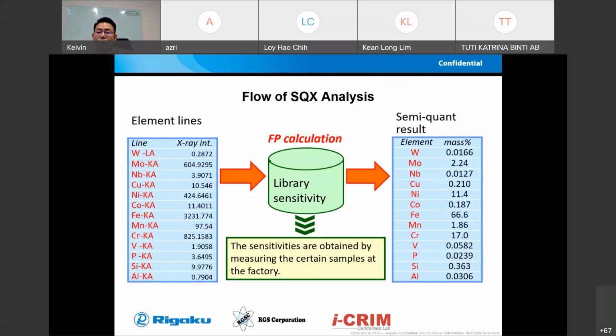So for the semi-quantitative result, the accuracy could be about 95% or even sometimes lower, like 85 or 80%. Because this is not a calibration method, but the advantage of this SQX, standardless measurement, is you don't really need to have the standard.